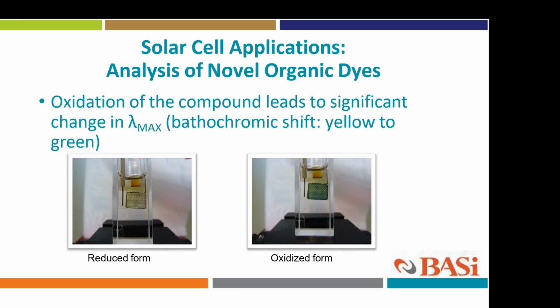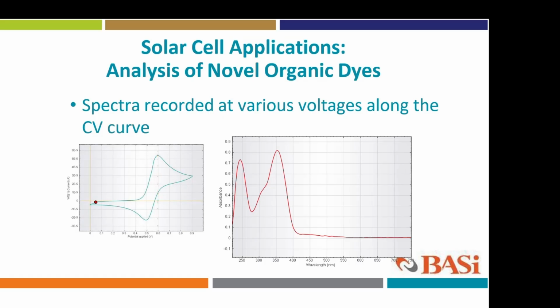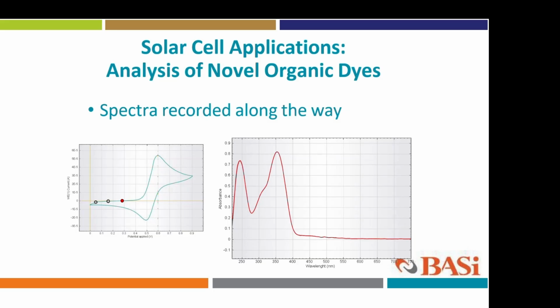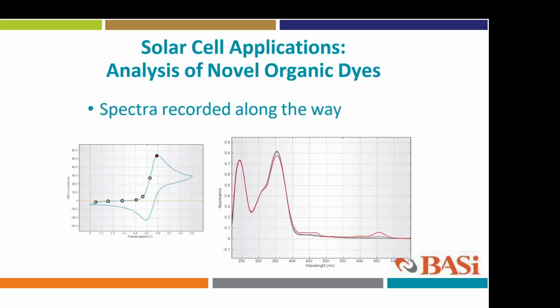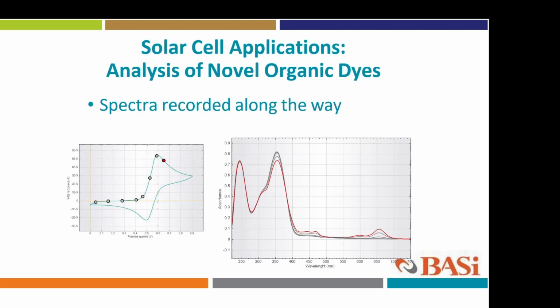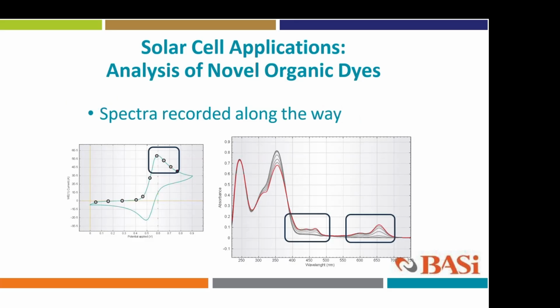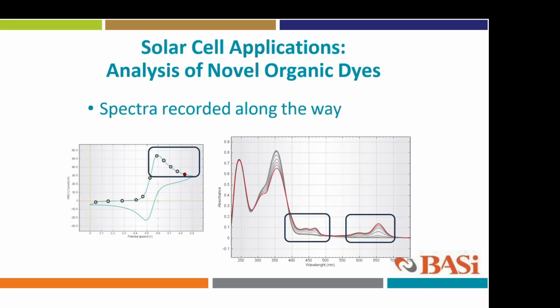Say, for example, a novel organic dye is in your hand. You can do an oxidation of the compound. Usually, it will be a bathochromic shift. You will have a yellow to green color change, and the way you do it is you simply record UV along the cyclic voltammetry curve, and immediately as the oxidation begins, or say you hit the oxidation peak, you're going to see those curves that correspond to the oxidation or the radicals that are actually coming out, and you will immediately understand how stable those radicals are as you prolong the reaction.